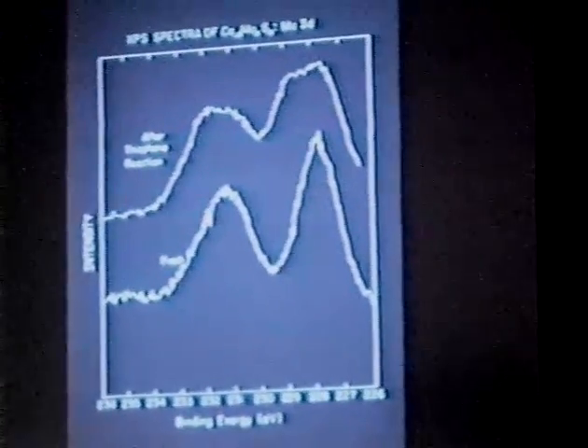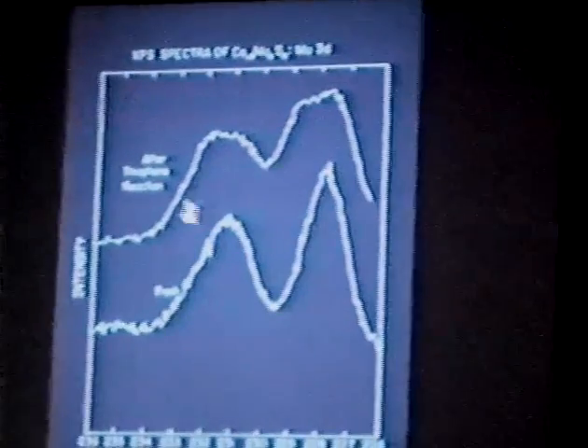Here's typical XPS data. And actually, it's not very typical in that the vast majority of the Chevrel phase compounds did not demonstrate any change in the molybdenum oxidation state as a result of use in hydrodesulfurization. Most of the molybdenum 3d 5/2 peaks are around 227 eV, 227.7 I think eV, compared to 228.9 I guess for MoS2. There were a few compounds such as the cobalt Chevrel phase compound that did show some change in the molybdenum oxidation state after use, and this is again reflecting probably oxidation at the surface to form some MoS2.